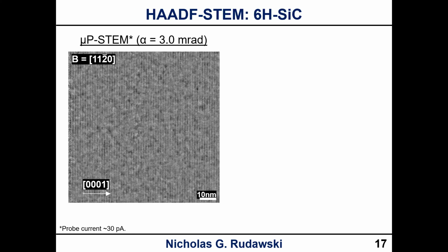But it's really interesting to see if we look at a material with a large lattice constant. So 6H silicon carbide, it's a hexagonal lattice, and its c lattice constant is about 1.5 nanometers. If we're looking down the [112̄0] zone axis, we can actually resolve this. In the STEM image here, you can see those vertical lines that correspond to the 0001 d-spacing for 6H silicon carbide.